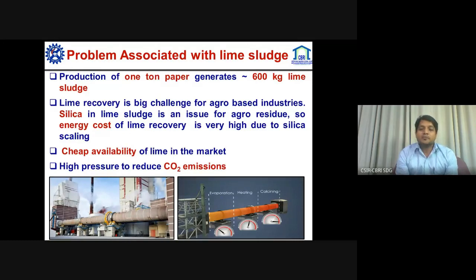So, as you can see in lime kiln operation, there are 3 stages: one is evaporation, second is heating, third is calcining. Evaporation and heating are okay, but in the calcining process at the third step, this silica causes a scaling problem in the lime kiln. So the process becomes so energy intensive, and hence it's not cost effective. It's not worthy for paper industries to use lime kiln operation at this energy cost.